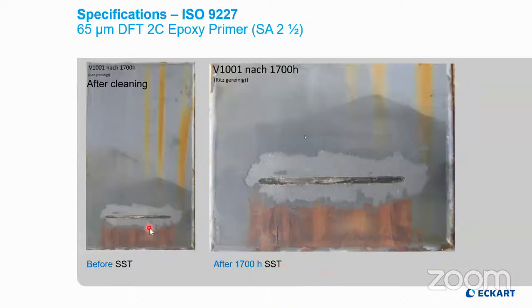We have removed the paint film from this panel as just shown. And this is an enlargement of the cut here. So the evidence to display to you that this rusting is not occurring, is successfully prevented by using zinc flake pigments.